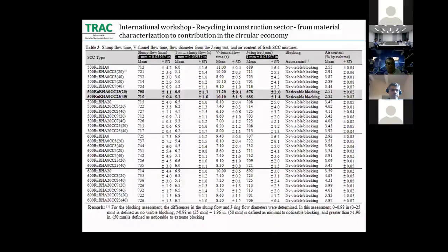By controlling the HRWRA, high range water reducing agent, along with powder contents of 500 and 600 kilograms per cubic meter, it was found that the slump flow of self-compacting concrete containing calcium carbonate significantly increased, because CC required a large amount of water to reach the required slump flow criterion, which is consistent with the air content value of the self-compacting concrete mixtures. This effect also occurred in the self-compacting concrete mixed with rice husk ash with increasing powder content. In addition, increasing the calcium carbonate content from 20 to 40 weight percent can improve the slump flow, increasing from 721 to 732 for the controlled self-compacting concrete.